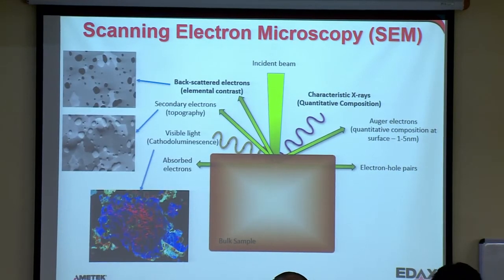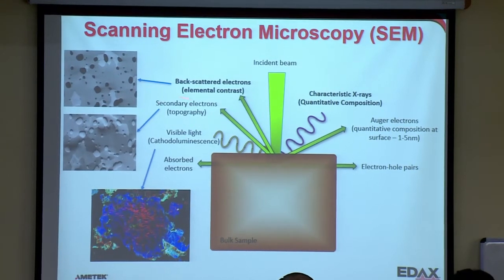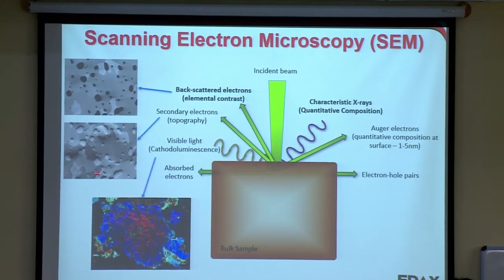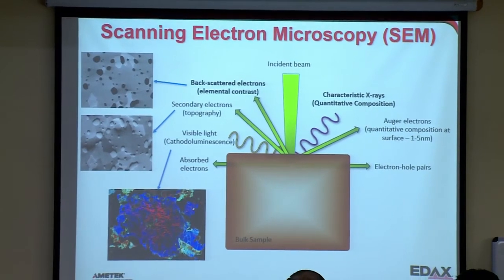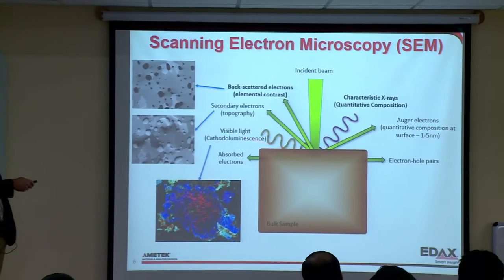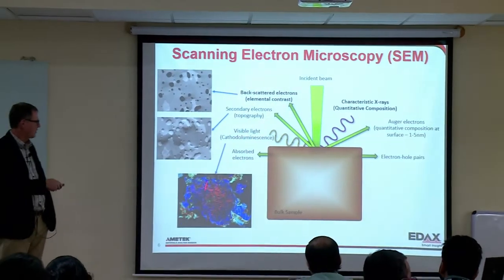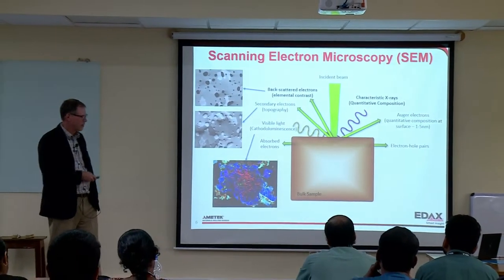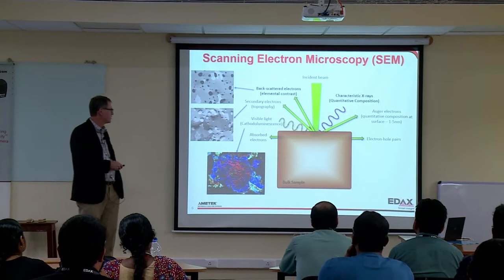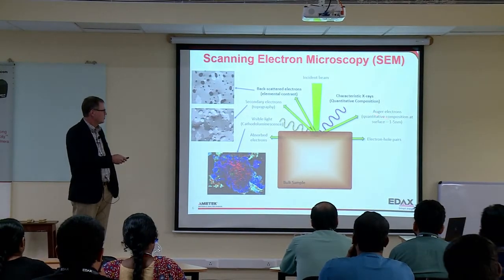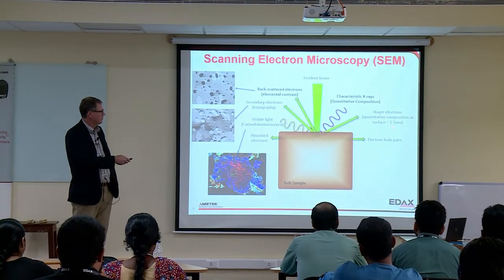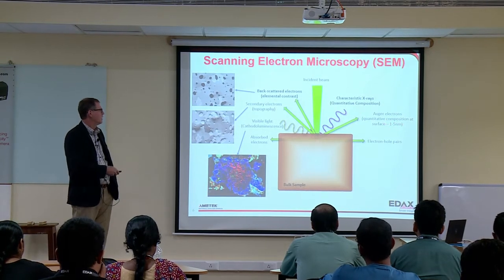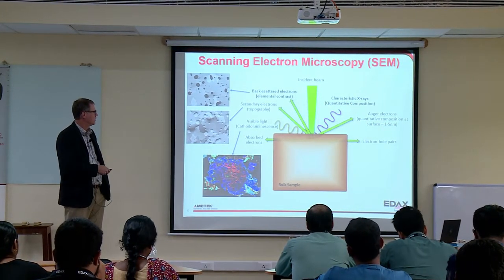Now, what do some of these images look like? Backscattered electrons, generally we think of those as providing Z contrast, elemental contrast in the microscope. Secondary electrons generally give us an idea of the surface, what the topography or topology looks like. Visible light, most commonly we think of cathodoluminescence, which tells us something about the chemistry and state of the material. And there's Auger electrons, they also give us composition very much right at the surface. And there's characteristic X-rays, which we will talk about too.